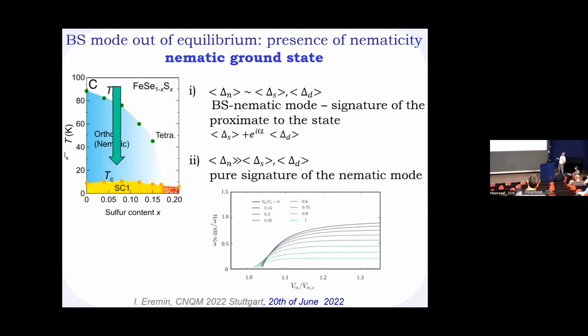But in this case, you can study the dynamics of this mode, and you see that it becomes a signature of proximity to the state which was originally discussed by Jian Kang and Andrey Chubukov, where you can have a relative phase difference between the s and d-wave components, simply because once you have a nematic order, the mixture of s and d is basically by virtue of the biquadratic coupling to the nematic mode. But if there is an intrinsic instability, you will be able to see it as an additional mode. And you can probe its dynamics. It has a very peculiar dependence that I don't have time to discuss.